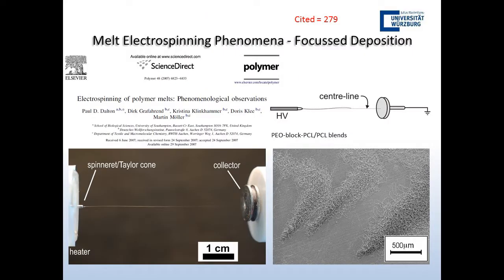One of the things, and this is now 2007, I noticed when we were having certain formulations, you could get these really, really long jets, and what it was doing was electrospinning just above the surface. So you were able to have like a focus point, and you get these tiny little spurts of very nice quality fibers from melt electrospinning. And this paper was so hard to publish. Yeah, it was back and forth, reject, and it was really, really difficult.